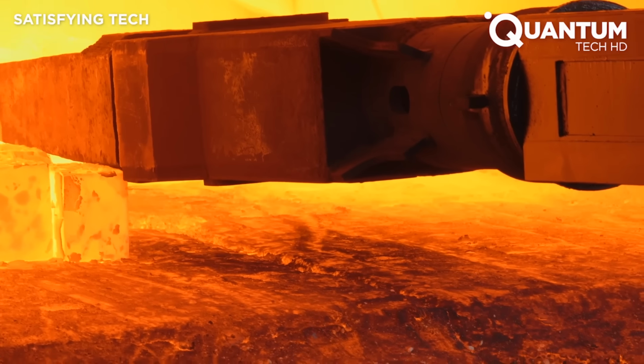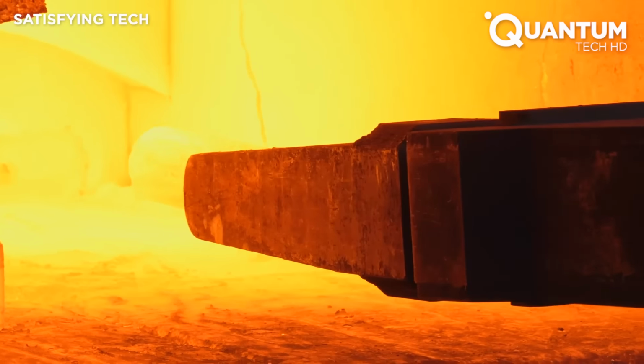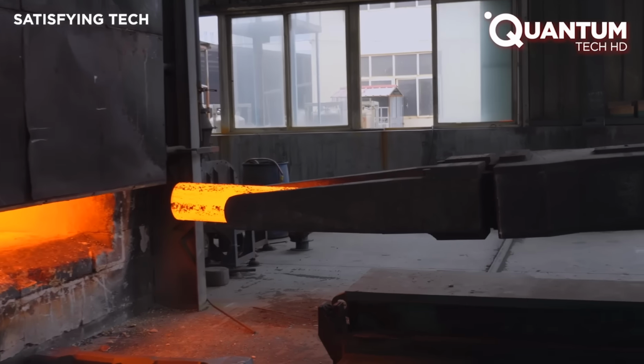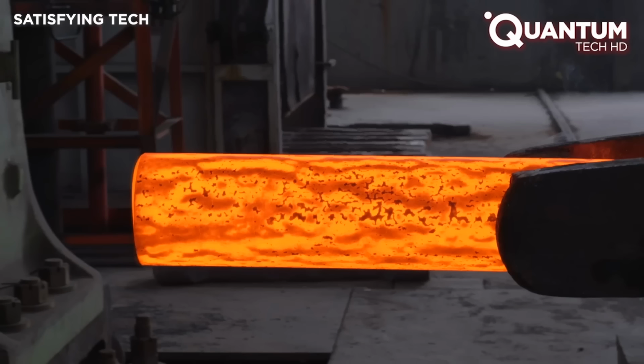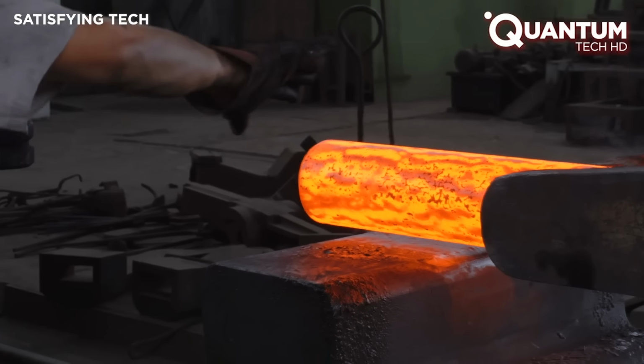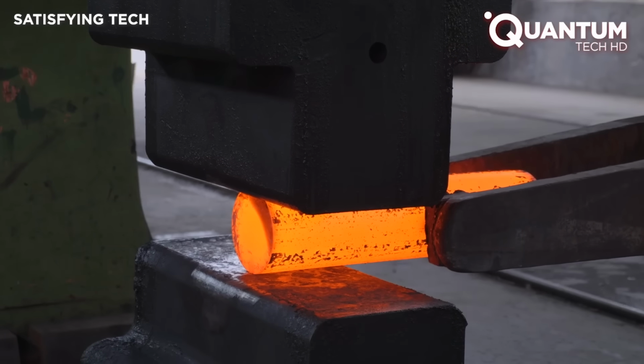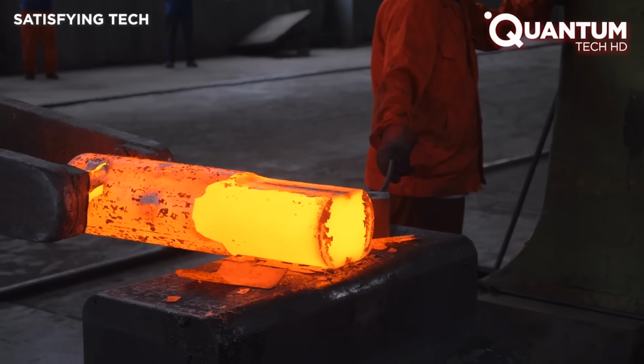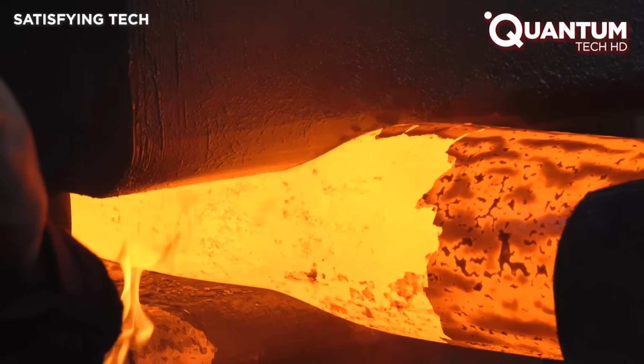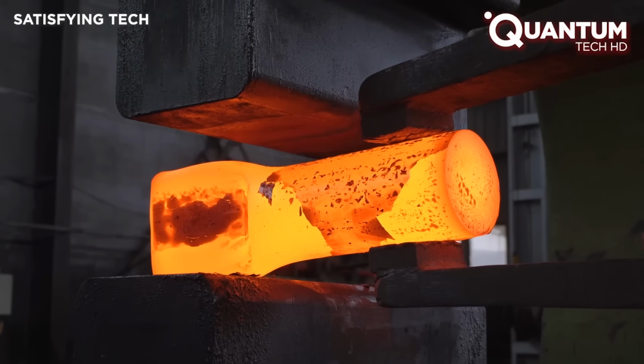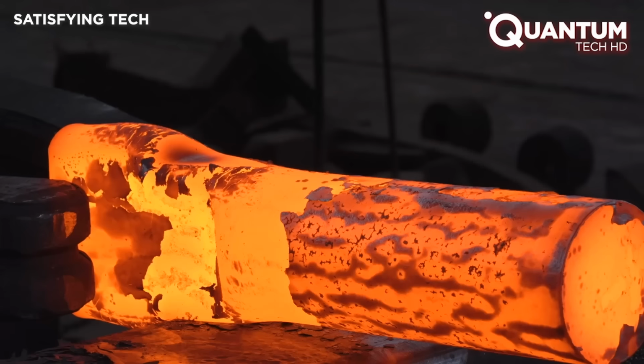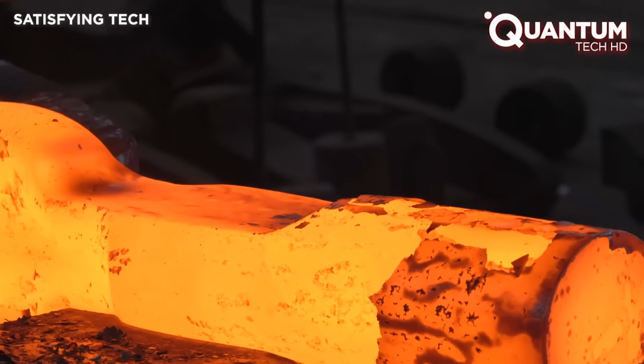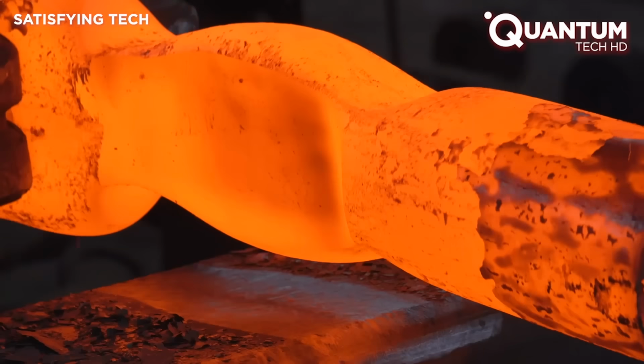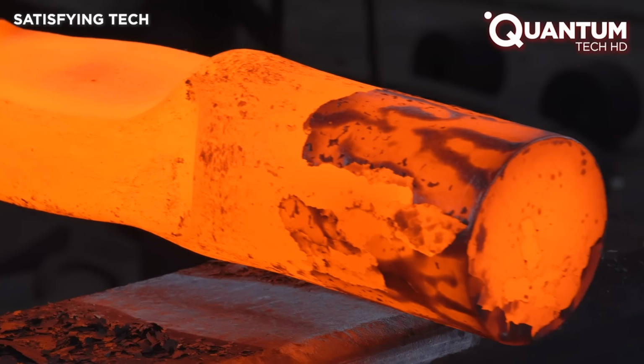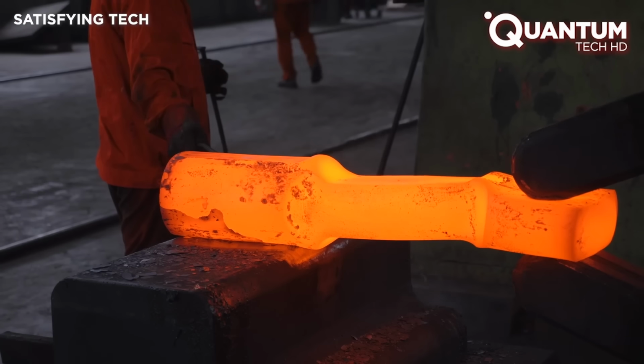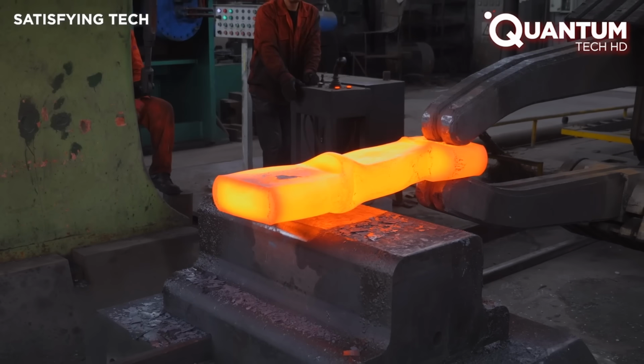After hours in the furnace, a special vehicle extracts the ingot. The incandescent color indicates that it has exceeded 2,200 degrees Fahrenheit and is ready for the press. The ingot is then placed under a forging press. With a force of 6,000 tons, the first blows begin to compact the metal, modifying its internal structure and improving its mechanical properties. A manipulator arm holds the piece while the forge continues to strike it to create the wider ends that will later become the shackle ears.